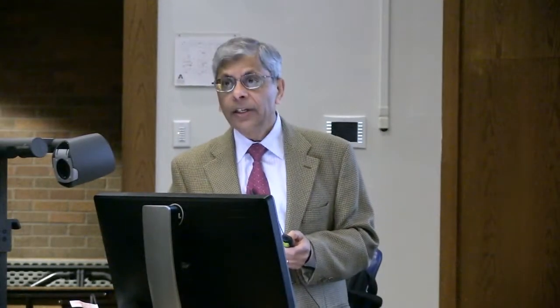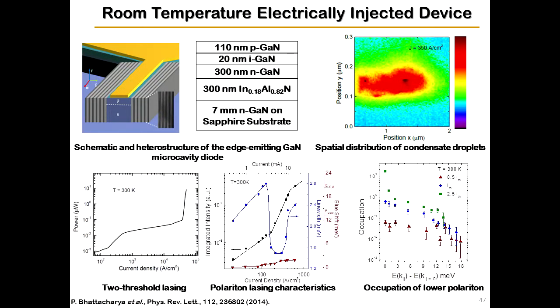And finally, of course, the race was again to get an electrically injected device. This is all optically pumped, and I have always believed that an optically pumped device is to understand the materials and the physics, but for applications, you really need an electrically injected device. And several groups around the world were working. So 2 years ago, we demonstrated the first electrically injected device, but that was working with gallium arsenide material, which works at cryogenic temperatures. And that's no good either. You're not going to move around with a cryostat in real applications. So we had to make a real room temperature device.